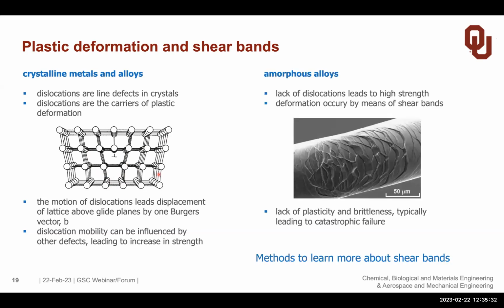But if you go to an amorphous alloy, you have no lattice and you can have no lattice defect. So the lack of dislocations typically leads to a high strength because the material cannot deform by dislocation motion. But it also means once it deforms, it's a catastrophic failure. And you see that over here, shear bands run through the amorphous alloy and it catastrophically fails. We call it the material is brittle.